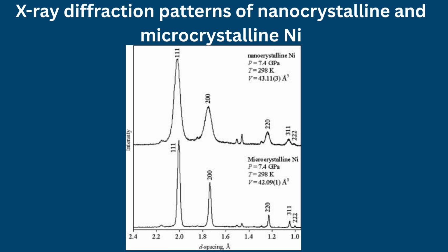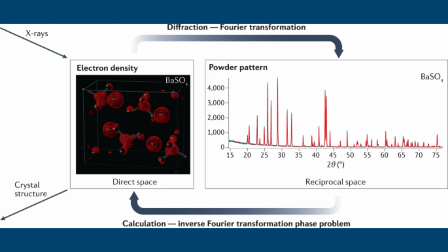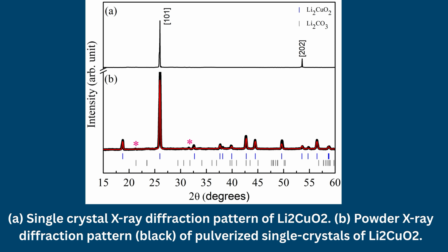For example, narrow and intense diffraction peaks generally indicate highly crystalline materials, whereas broad peaks may suggest nanocrystalline domains or structural disorder. In powdered samples, millions of randomly oriented crystallites contribute simultaneously to the diffraction pattern. This random orientation ensures that multiple crystallographic planes satisfy Bragg conditions during measurement, enabling complete phase identification. In contrast, single crystal diffraction focuses on an individual crystal to determine precise atomic arrangements and symmetry relationships.